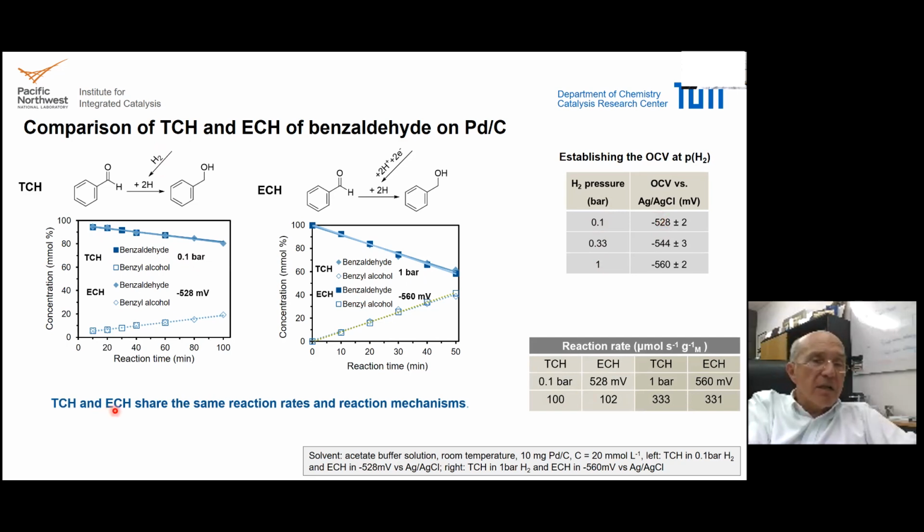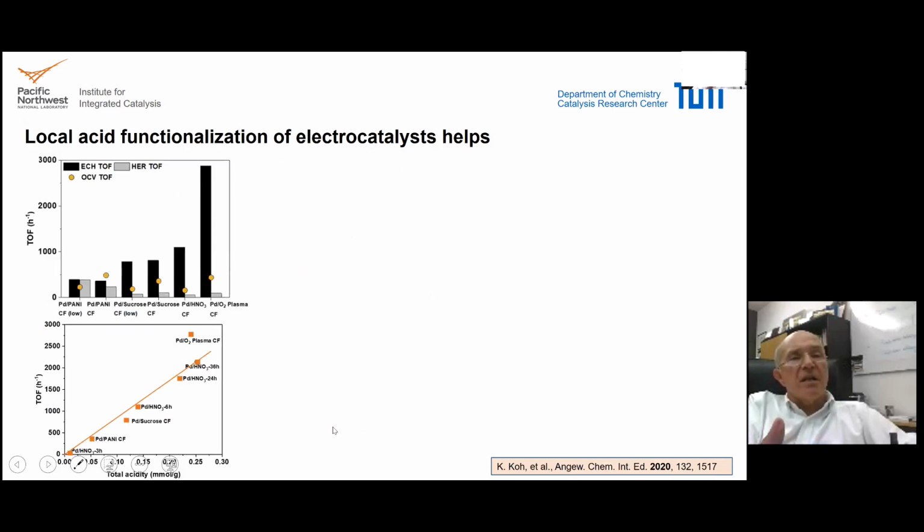That means for us, thermal chemical hydrogenation, the addition of hydrogen, and electrochemical hydrogenation share the same reaction rates and the same reaction mechanisms. So we have to deal with this in the same context, and therefore we will investigate whether a local charge will shift, and local hydronium ion concentrations will shift again the mechanism.